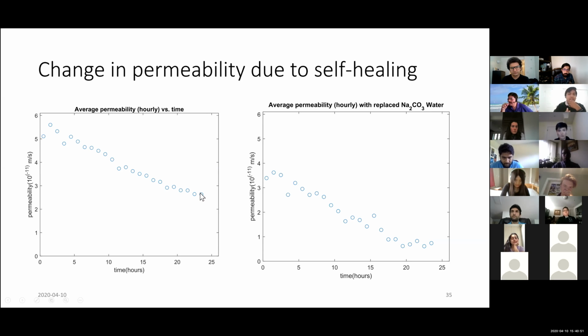Then I remove all the water from the system. I replace that with sodium carbonate water, which is saturated up to 10% by volume. And then again for the next 24 hours, I observe the average permeability every hour. From these two, we can see that this one is slightly higher. And even after replacing with sodium carbonate, the permeability goes down and reduces even to further smaller values. So we can say qualitatively that the sodium carbonate is helping to reduce the permeability even further.